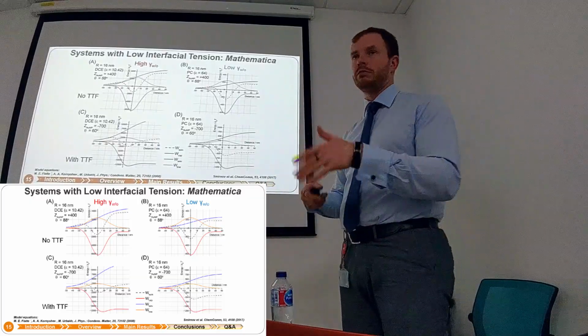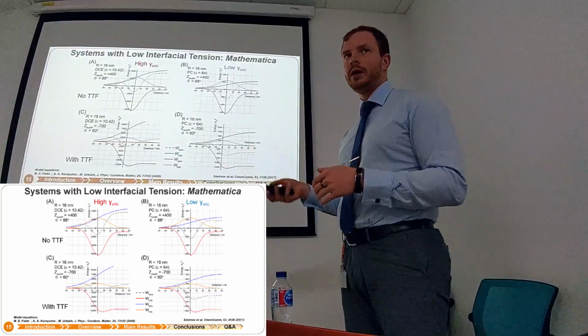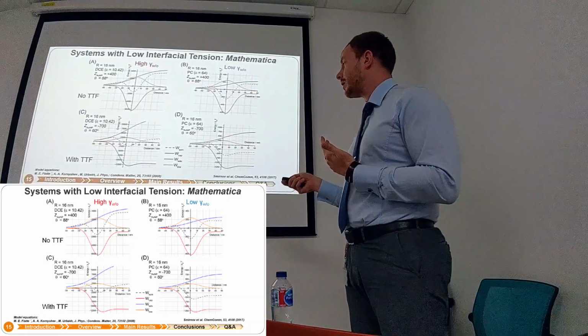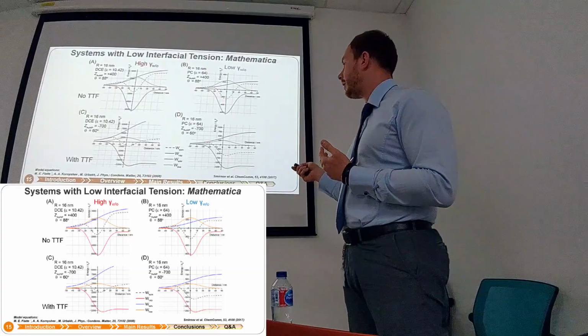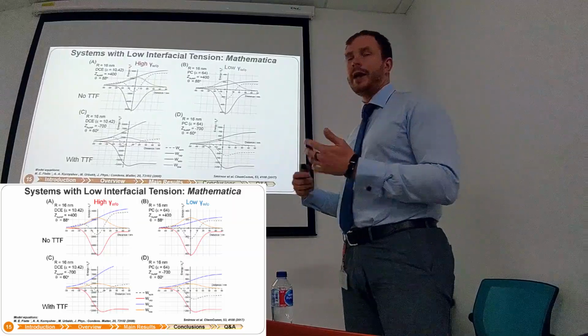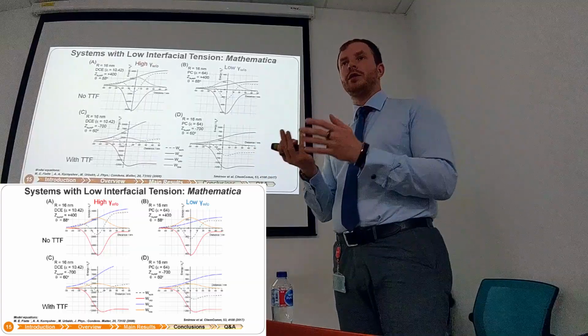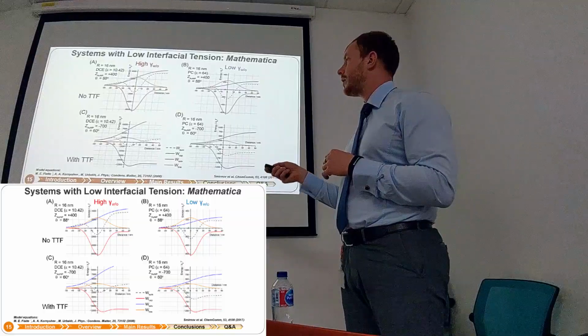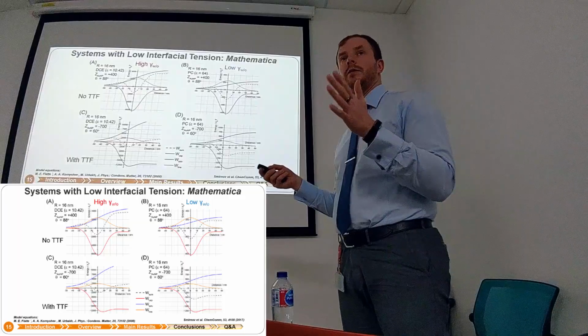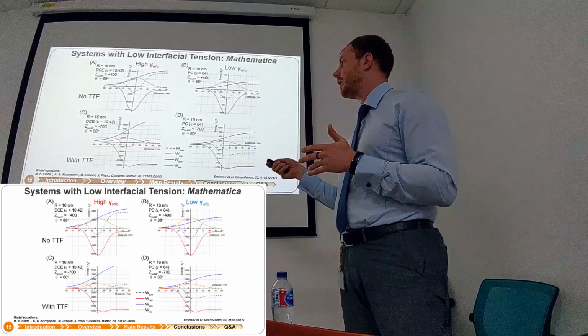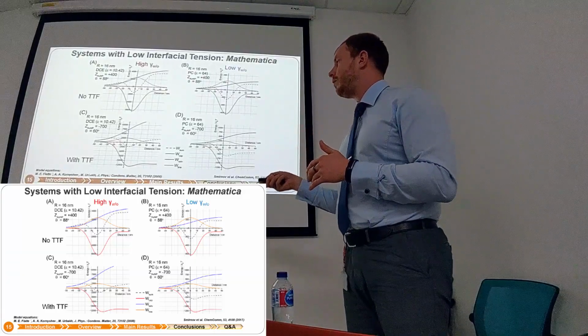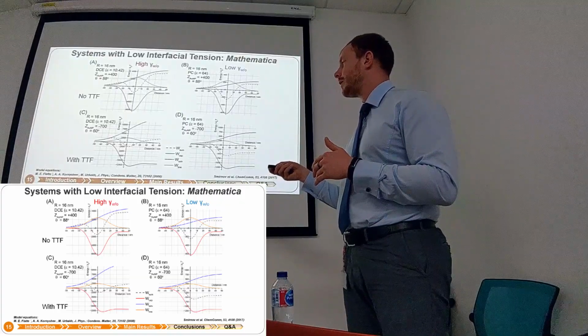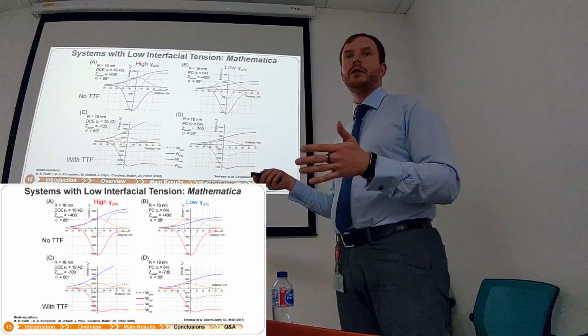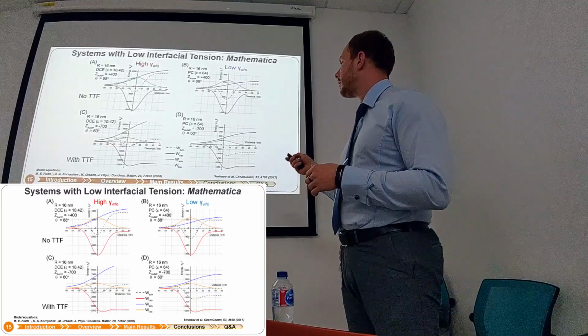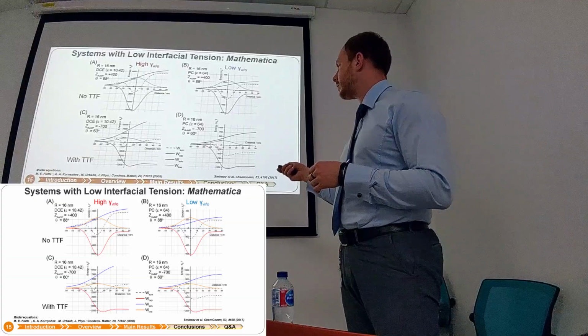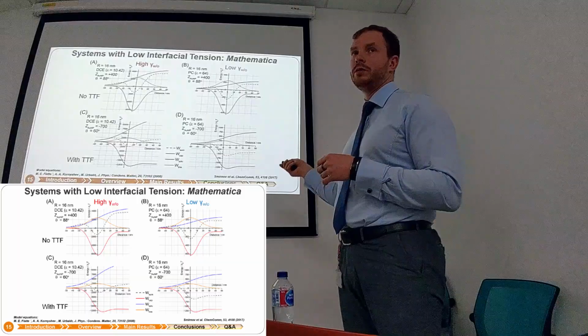So if we consider from first principles, not the big maths behind these graphs, but different interactions like capillary forces, solvation forces that are of course higher in the organic phase than in the water phase, some line tension that depends on the curvature of the interface around nanoparticles and so on, it's very clear that without TTF we have quite a big barrier that protects nanoparticles from reaching the interface. So literally, nanoparticles don't know that there is a potential well where they can go. If we add TTF, then this potential barrier can be overcome by shaking, for example. So it's enough energy to overcome this barrier. And the same is happening here, except that when we add TTF, there is no more barrier. So it's a small well, and then nanoparticles in principle can go to the organic phase.